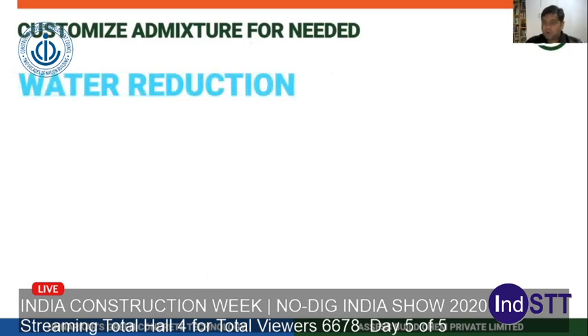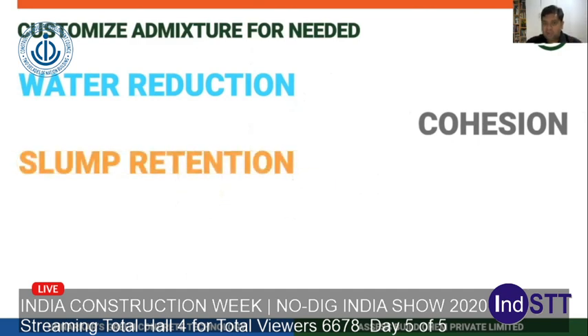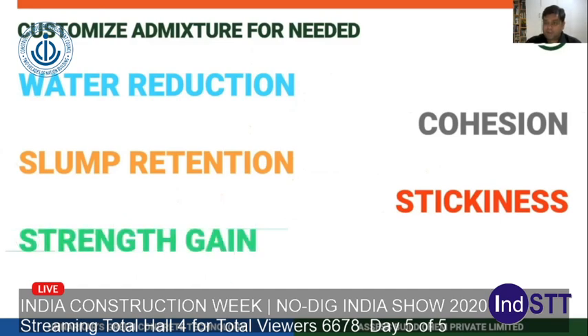So we put together a mix with modern admixtures like PCE. We are using the best of all the materials, the formwork with the PCE, and even with the PCE, a bit of customization was needed. So water reduction, the cohesion, the slump retention, stickiness, a lot of these different aspects, the strength gain part of it, and the flow, of course.